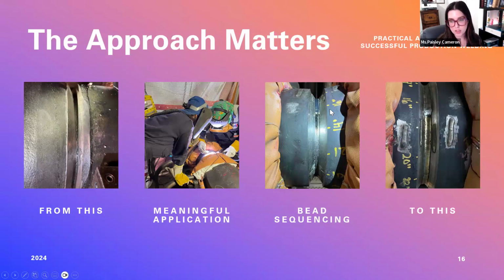In this particular case, we utilized, very unorthodoxly but successfully, that crack as the root gap instead of completely removing it, because if we had completely removed it, there would have been significant changes on the actual full system, and the owner user was not willing to take that risk. So you can see here, we used specific bead sequencing of a very specific consumable size, diameter, etc., to complete the weld. So there we have the weld completed, and once you complete over those cracks and do the appropriate inspections, we're able to fill it appropriately as required.